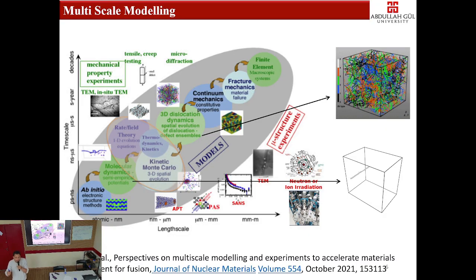You can easily activate the edge dislocation. That is why you can have plastic deformation at the early stage of deformation, right? But think about any BCC material, like tungsten. They are very hard because they deform with screw dislocation, which is thermally activated. It is not edge dislocation. So one thing to be familiar with is edge dislocation.